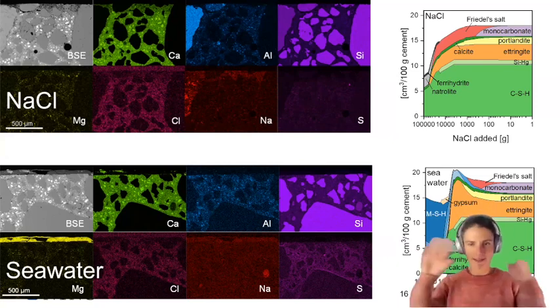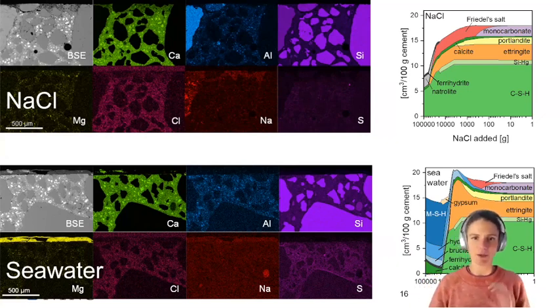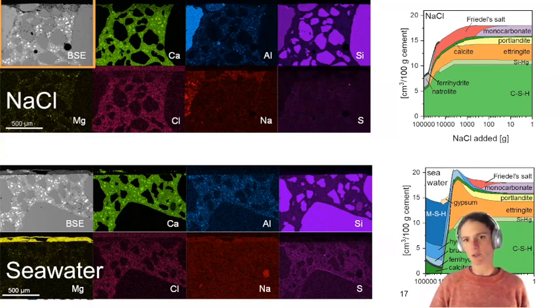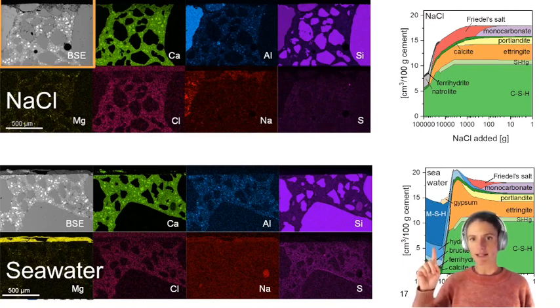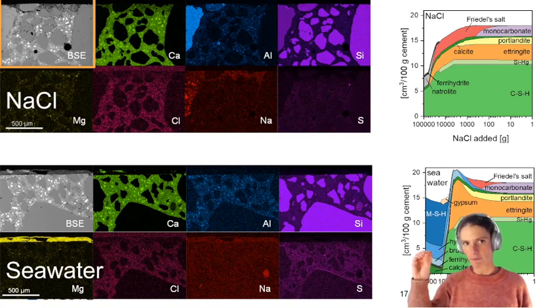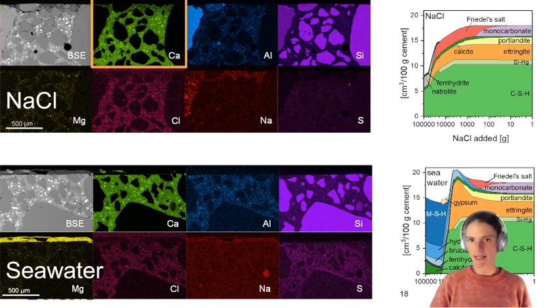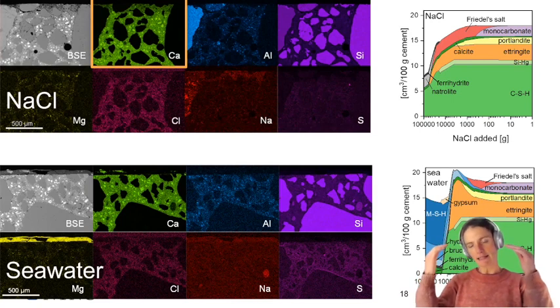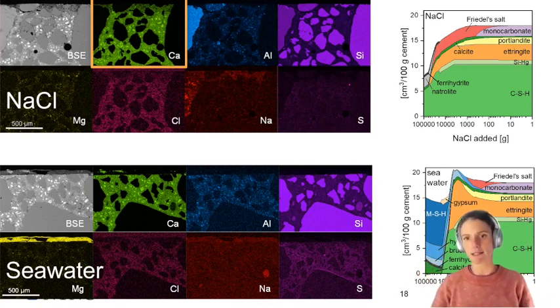But in order to guide your eye, because this is a lot of information in one slide, I'm going to put some boxes around the maps I'm talking about. So let's start with sodium chloride exposure and look at the backscatter electron image. The top of these images is the exposed surface. And we can see that on the top, it's getting slightly darker in the cement paste. So it looks like we might be losing material upon exposure to sodium chloride. And that matches with the calcium map, where we see that the cement paste, which is rich in calcium, is getting slightly darker at the top, so we're losing calcium in our cement paste.